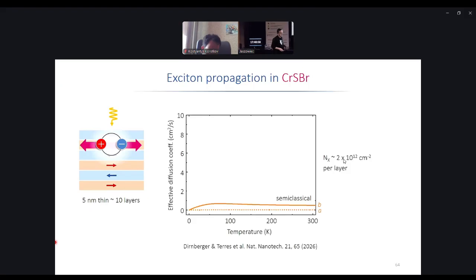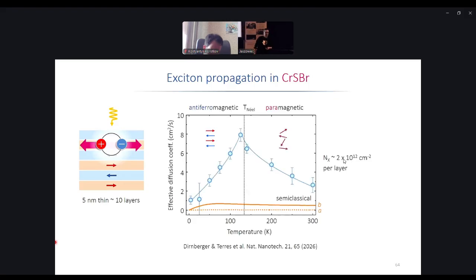There are materials that combine magnetic and optical excitation, so a lot of people these days working in the van der Waals field are interested in materials such as chromium sulfide bromide, which is an antiferromagnet, which also hosts excitons. And in this case, also in transport, one finds interesting phenomena such as the actual diffusivity deviating as a function of temperature from semi-classical predictions, which you see here, but instead correlating with the magnetic phase transition. Yeah, and there are additional phenomena associated with this. The diffusion is nonlinear. There is sometimes super-diffusive behavior at 5 Kelvin. But in this particular case, the transport of excitons reacts to the transition from antiferromagnetic to paramagnetic phase.